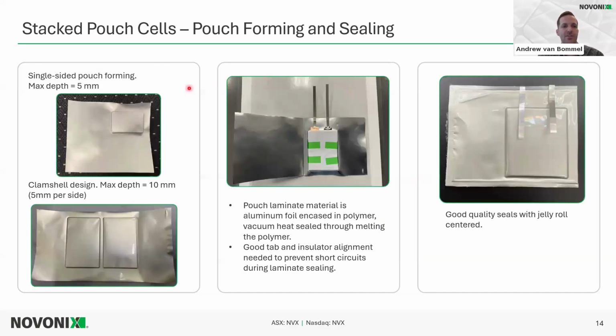So the next step of stacked pouch cells is pouch forming and sealing. So first, a pocket or a form needs to be formed on the pouch material. So this pouch material is aluminum foil encased in polymer. And so when that pouch is formed or that pocket is made, we can achieve a max depth of about 5 millimeters. If we go higher than this, there will be wrinkles and possible areas where electrolyte can leak out. So to increase this depth where we can place the stack, we can use this clamshell design.